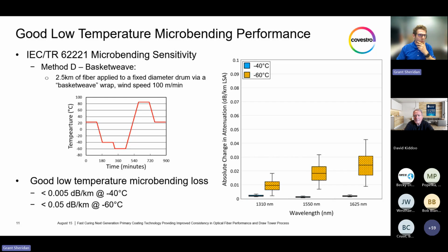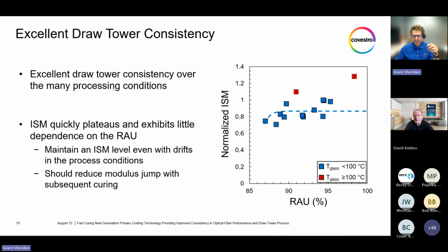So I understand the question. Due to this being a primary coating, you would have a secondary coating on top of it, so we wouldn't anticipate it affecting the ribboning and all that. But on the second half of the question, in terms of cabling, curing and ribboning, and losses, we would anticipate a smaller in situ modulus jump relative to our current technology. So we would anticipate smaller loss there, as the in situ modulus doesn't jump up as much. But we're still developing this technology, and would be happy to work and evaluate that with you as well.